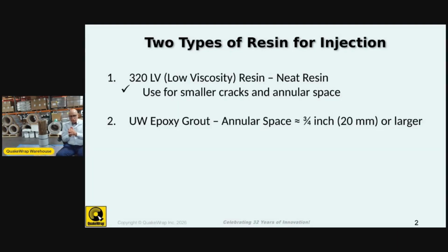So basically we have two kinds of epoxies that can be used for filling the annular space. One of our products is called the 320 LV, for low viscosity resin. This is a neat resin that has very low viscosity, and it can fill all the voids and cracks of a timber pile if you're filling it. Usually for these, keep in mind that neat resins, if you have them in large volume, when they cure, they shrink and crack. So it's really best that you blend them. If you have larger volumes, you want to blend them with some aggregate or fine sand to make sure that you avoid that cracking. And that's really what becomes that epoxy grout, which is the second type of fill material that we use. Typically with epoxy grouts, we go with an annular space of about 3/4 inch or higher, just based on whatever seems reasonable for the project.